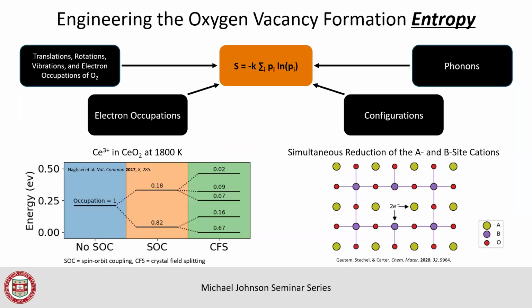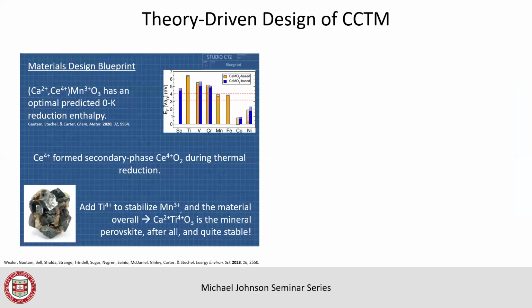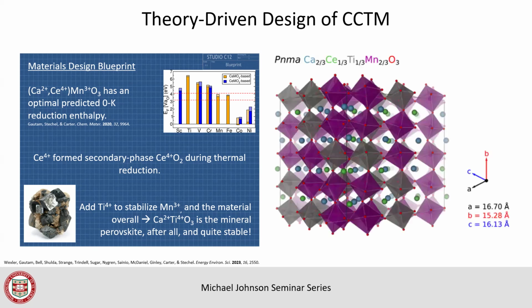Okay, not going to talk about entropy. But we use this and we said, let's find elements that we can put on this A site and this B site that have the right properties. And what we found was actually that if you put calcium and cerium on that A site, that box corner site, and then you put manganese, and later on we find titanium on that other site that has that nice octahedral arrangement of oxygens around it, this material is predicted to be stable. So we do a calculation, it doesn't break down. And if we actually compute the energy required to knock that atom out, wow, it's like right in the range.